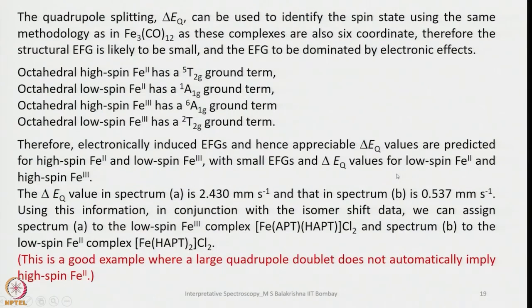So then how it is done: you can see here the quadrupole splitting value ΔEQ can be used to identify the spin state, using the same methodology as we used for Fe3(CO)12. As these complexes are also six coordinate, the structural EFG is likely to be small and the EFG to be dominated by electronic effects. Now let's look into these